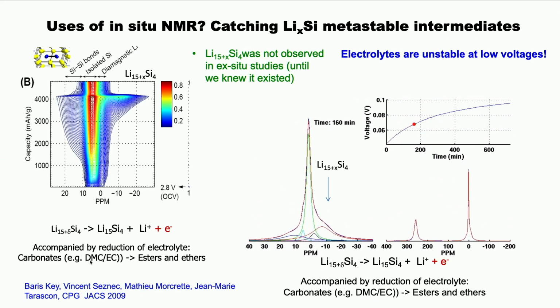So I just want to give you a little flavor of the sort of things we've learned over the years. The first study that we did was on silicon. Graphite has a capacity of about 370 milliampere-hours per gram. If you use silicon, you can react 10 times more lithium with it. And so it's been touted for many years as the ideal replacement for graphite.